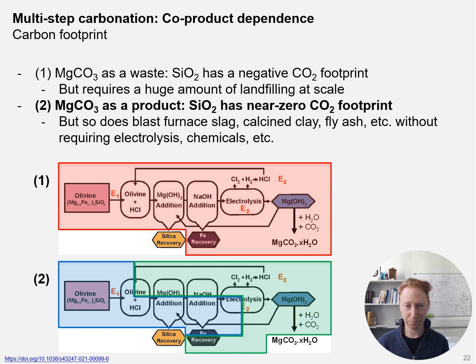So if we instead treat the magnesium carbonate as a product, where its sales are driving the CO₂ mineralization process, then the silica supplementary cementitious material has a positive but near zero carbon footprint rather than a negative one. And that's because the CO₂ that is being mineralized is being accounted for in the part of the product system shown here in green that is associated with the magnesium carbonate product. So in this case, we produce a near zero carbon emissions silica supplementary cementitious material, and that has about the same carbon footprint as common supplementary cementitious materials like blast furnace slag, coal fly ash, fine limestone, and calcined clays.